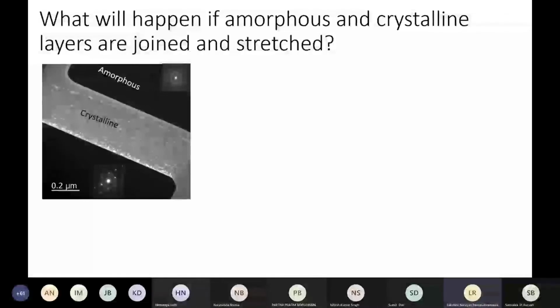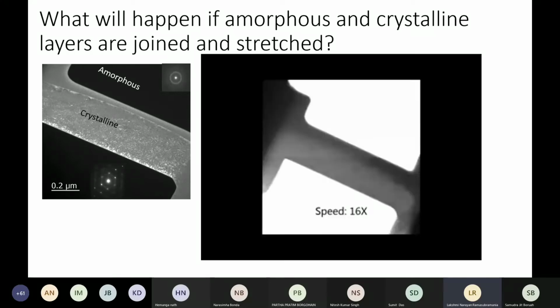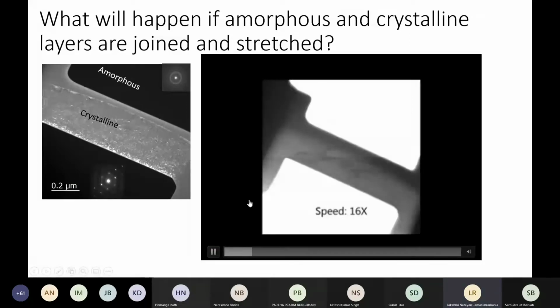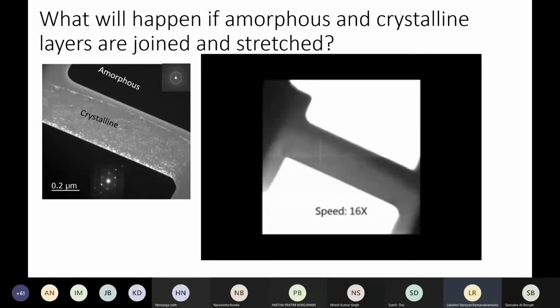So what we tried was we used an amorphous crystalline bilayer. It's a very interesting experiment in the sense that nobody knows what will happen if you stack them up together and you start stretching them. And in this experiment, we did exactly that. We used a crystalline layer which has a very similar crystal structure to the one we examined before, and then an amorphous layer which is very thin over this. And I'm going to show this video of the experiment which we did. It's very sped up because it's otherwise going to take a long time.